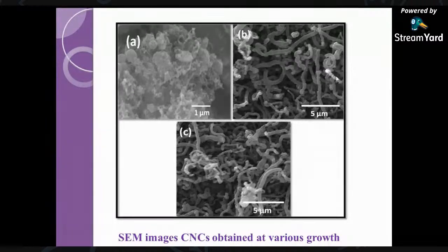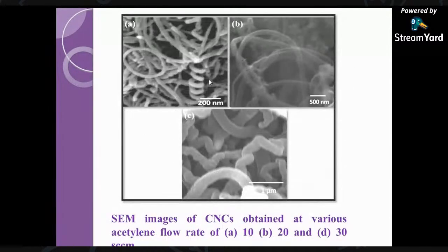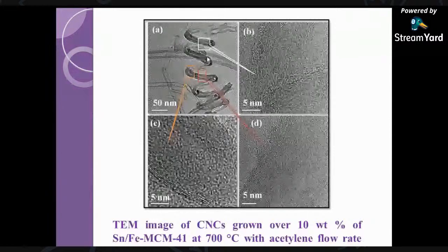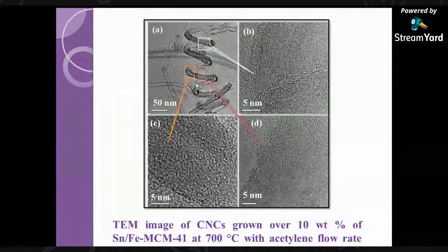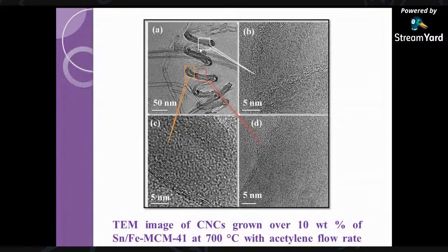So you can see a spiral shape of carbon nanotubes in this structure, which happens at a reaction duration of 10 minutes. And you can see more spirals happening in these structures. So we were able to come across more beautiful structures, a combination of spiral, spring-like or linear. Okay. So we have a lot of beautiful structures coming at different flow rates. And this we take to explain that we can create coil-shaped carbon nanotubes out of this catalyst, called the tin iron combination in MCM41. So you get spiral carbon nanotubes here.